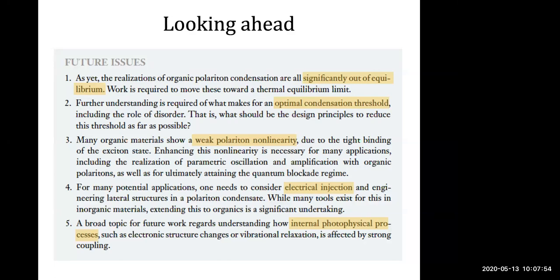But what you could do is try to pump directly through the mirror in a regime where the mirror reflectivity is very high, and then study the effect of circular polarization. This could be interesting in materials where you create some superposition of X and Y transition dipole moments, but this hasn't been done yet. Normally, the linearly polarized pump component will select some subset of your organic molecules, and this is what will break the symmetry of the system above threshold.